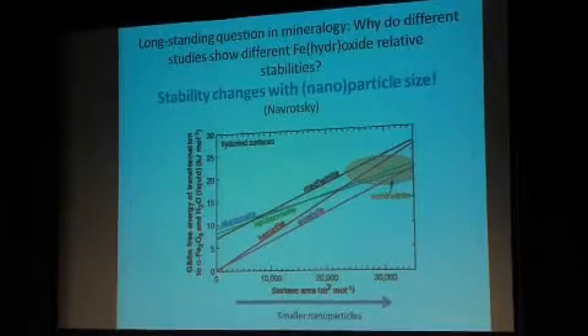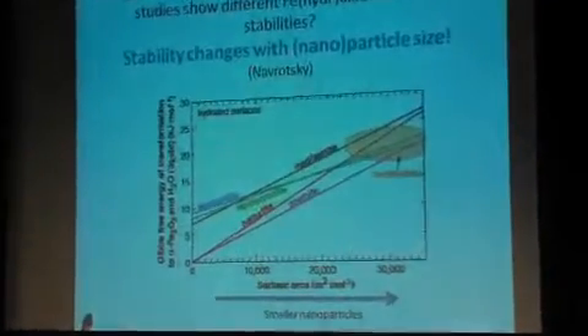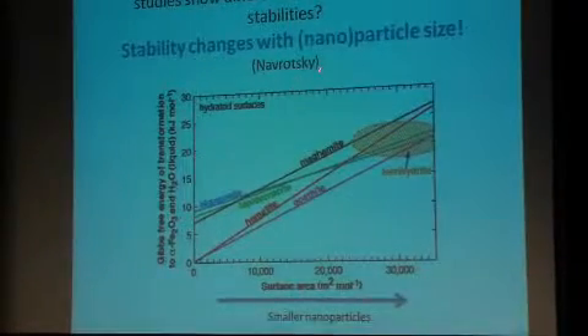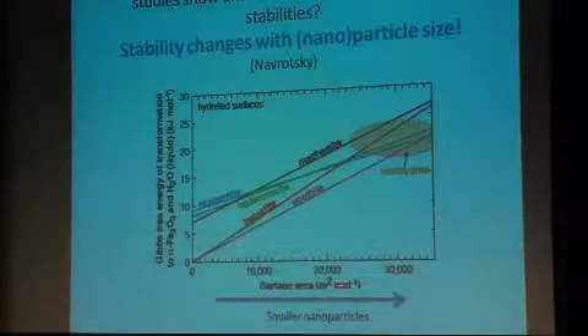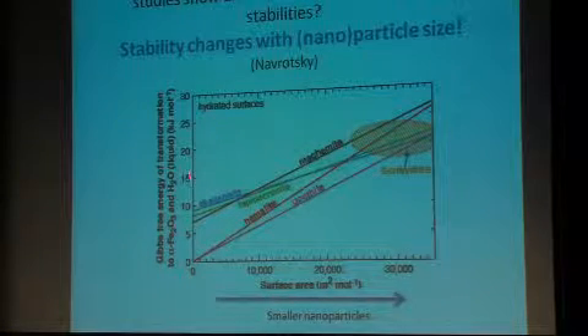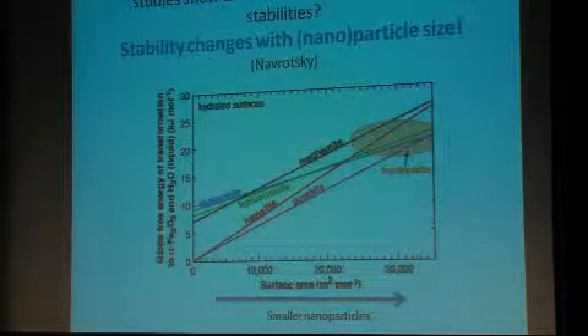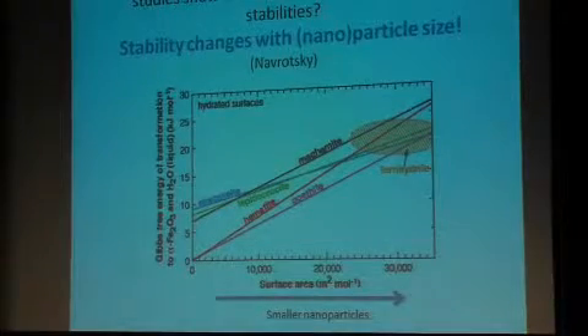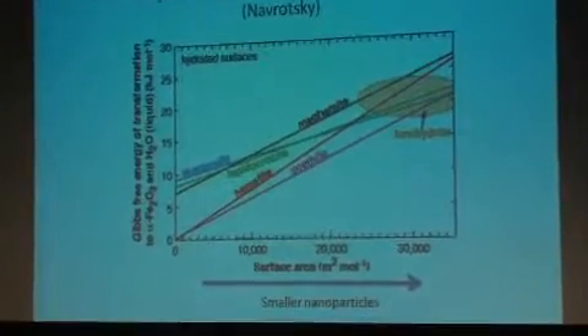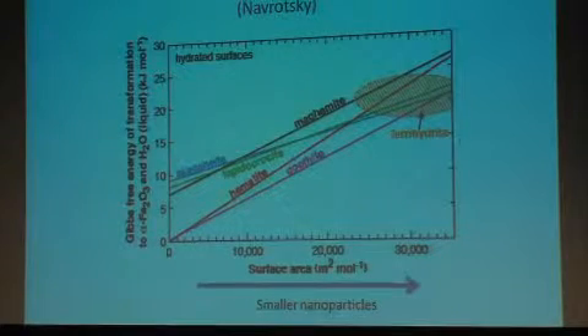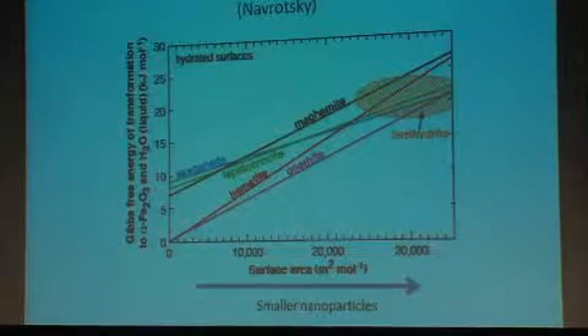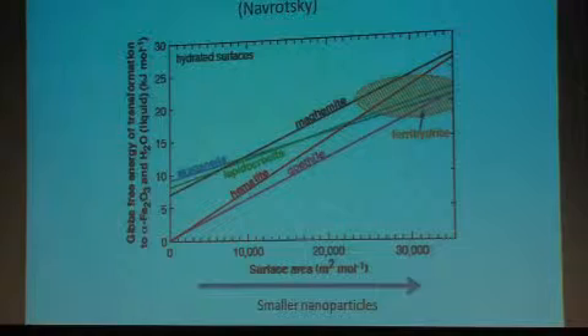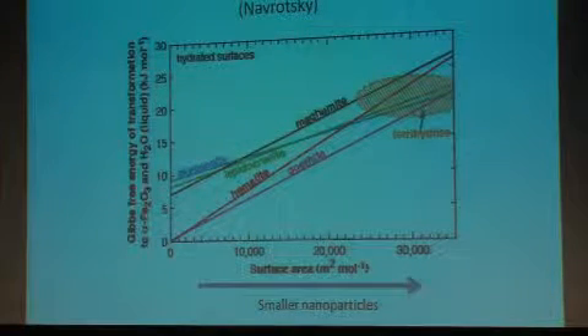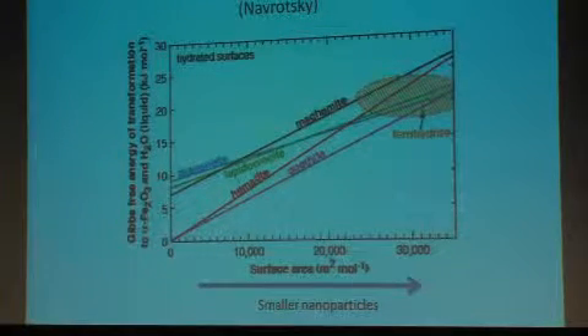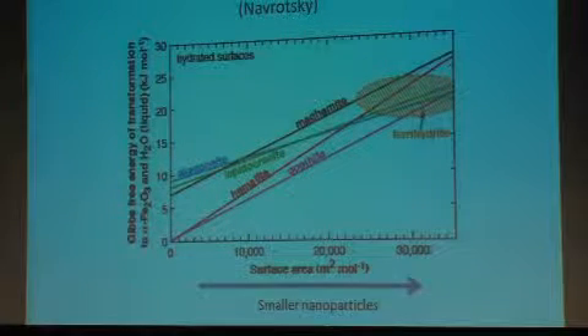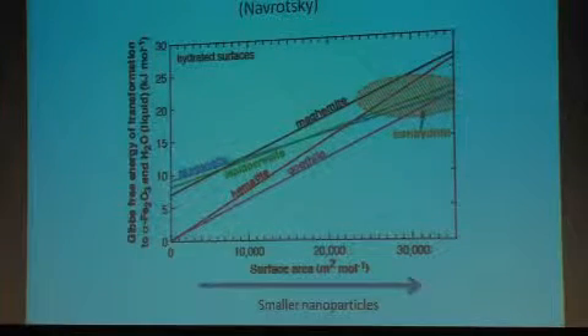This is some work done by the really great thermodynamicist Alex Navrotsky. As you go down in particle size, which means greater surface area, and you look at the energy associated with transformations, they cross over for the different minerals as you go to smaller and smaller size. So how they are stable relative to each other changes as a function of particle size, related to this surface free energy component becoming more important relative to the bulk, related to the change in structure, maybe related to some other things too that we need to further consider.